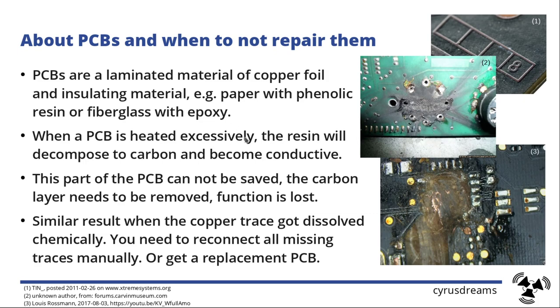If you heat that excessively, the resin actually will decompose, and you can see that in this picture. You can see at this point the weave of the fiberglass. All the epoxy resin is baked away, it's cooked away, and it's completely black. And it will decompose to carbon, and actually carbon is conductive. You use that for alternators and generators as brushes. So that one will now have conducting paths from that point to the opposite point. And you cannot have that on the PCB because that will completely change the function. So you need to get rid of that.